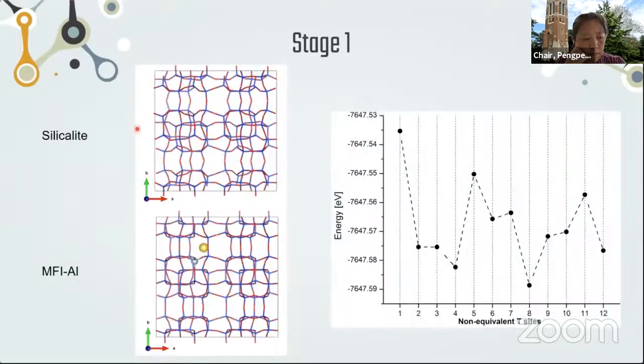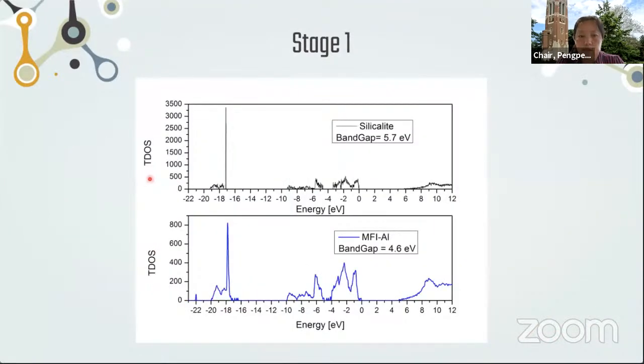This is the already optimized configuration, the representation for both silicalite and ZSM-5 with an aluminum atom together with the respective exchange cation, sodium in this case. The latter configuration comes from having previously determined the minimum energy position, which according to this figure is localized in one of the tetrahedral T sites. According to the total density of states for silicalite, we observe a band gap of 5.7 electron volts. When we introduce one aluminum, in this case in the MFI framework, the band gap is reduced to 4.6 electron volts.